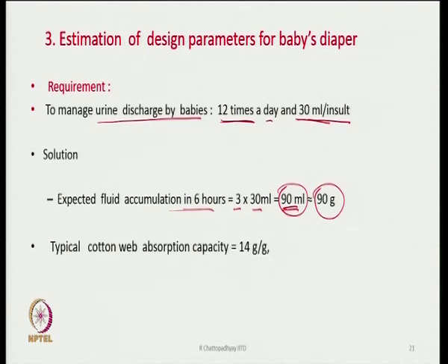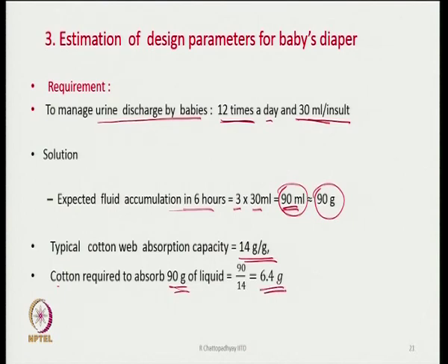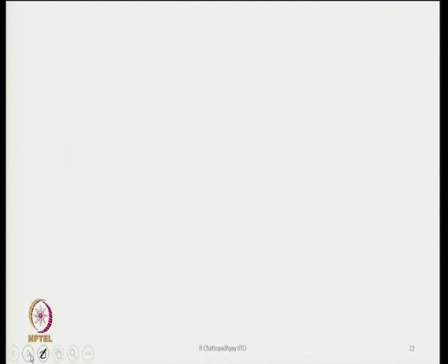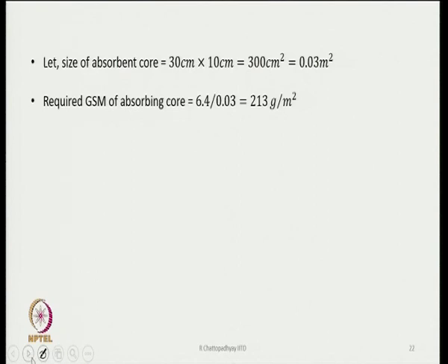So, typical cotton web absorption capacity is 14 gram per gram. This data will be available from literature, and if it is this, then the cotton required to absorb 90 gram of liquid is 6.4 gram. Okay. Now, the size of the absorbent core is 30 by 10, because we have seen the total length and breadth of a diaper. So, typically it could be, let us say, 30 into 10, 300 centimeter square, which is 0.03 meter square, assuming that it is just a rectangular piece.